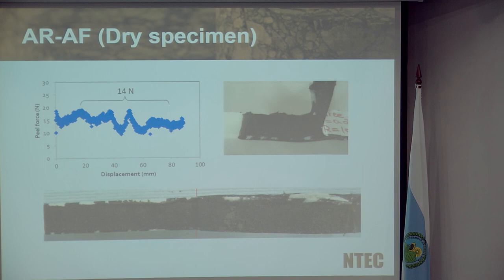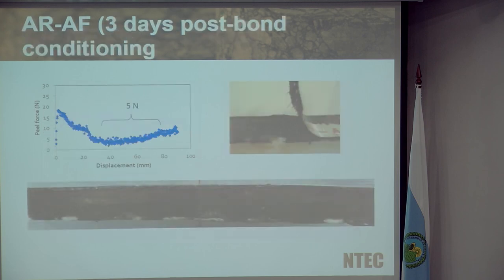And because water is not going to be able to diffuse as readily to the interface, we see that the behavior has only dropped down to about 5. So not only does the test allow you to understand the basic mineralogy of the aggregates in terms of ranking their performance, it also allows you to look at the effect of this water diffusion rate, which is important.